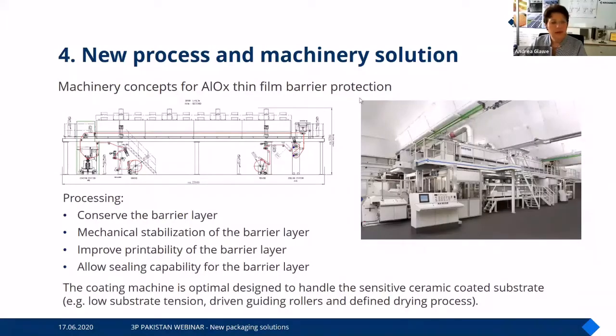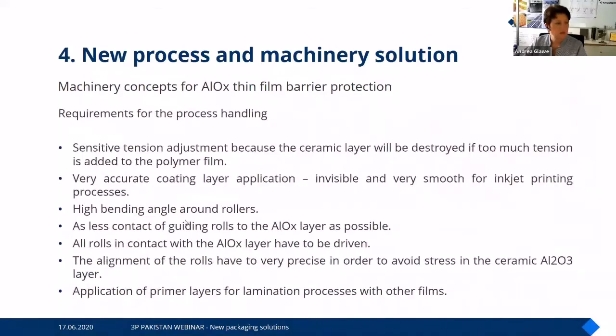When we go into AlOx thin film barrier applications, we need to realize with such a coating line the conservation and the mechanical stabilization of the barrier layer. We need to improve the printability, and we need to allow also, with an additional layer, the sealing capability of this highly sophisticated barrier. So this is what is realized with a wet coating process.